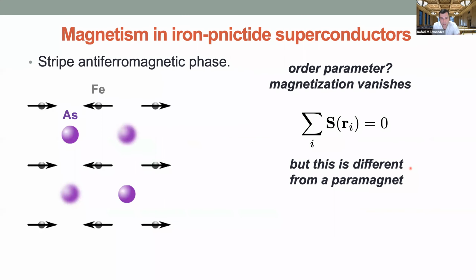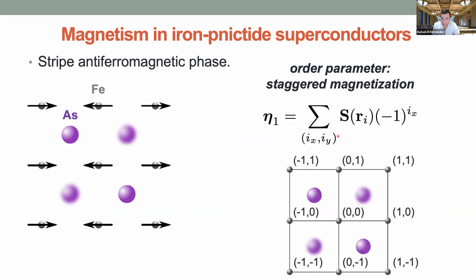If you look at this magnetic phase, you see that it's not ferromagnetism, it's actually a stripe antiferromagnetic phase, which means the iron spins are parallel along one direction and anti-parallel along the other. If I define an order parameter that is just the magnetization as I defined for the ferromagnet, I get 0. But if I define the staggered magnetization, where for every column I change, I multiply by -1, then I get a finite staggered magnetization.